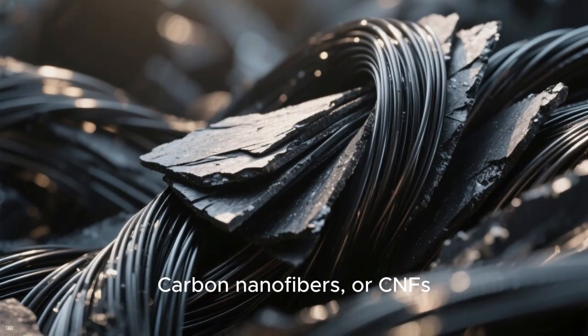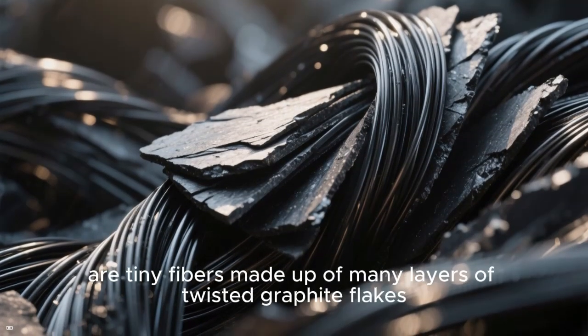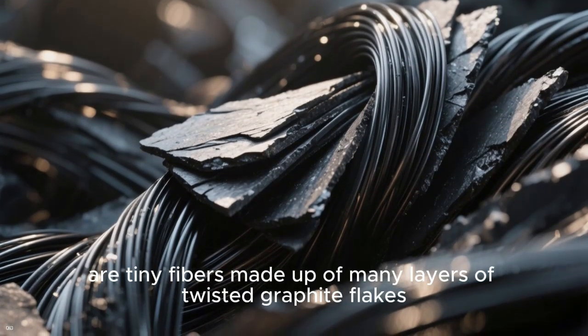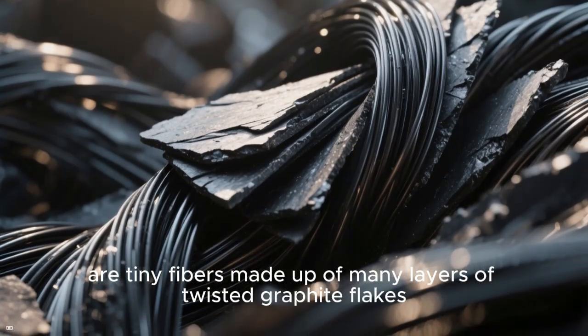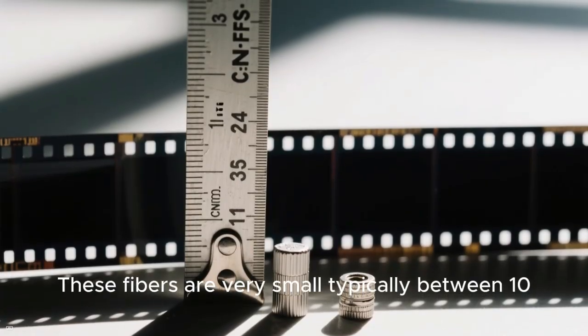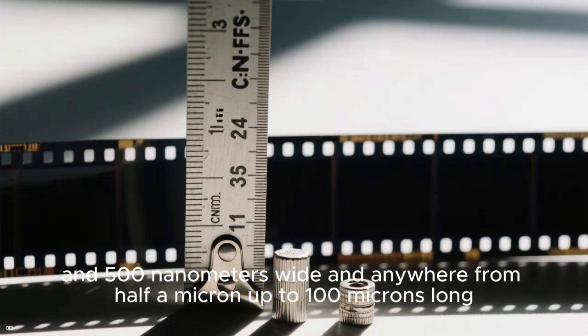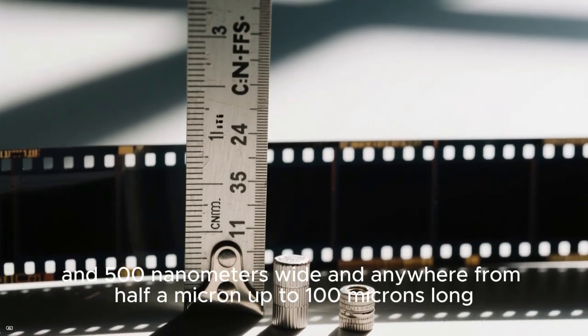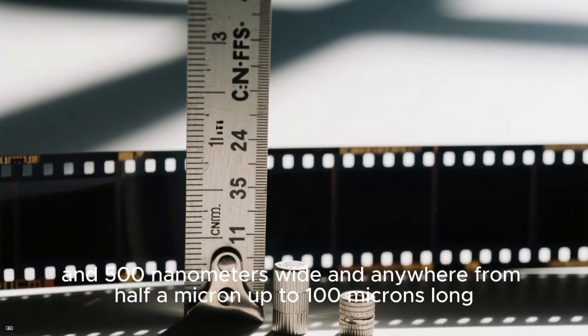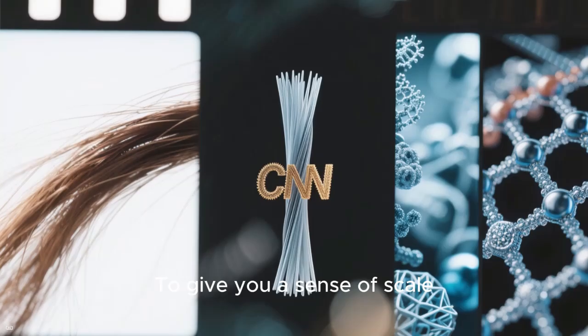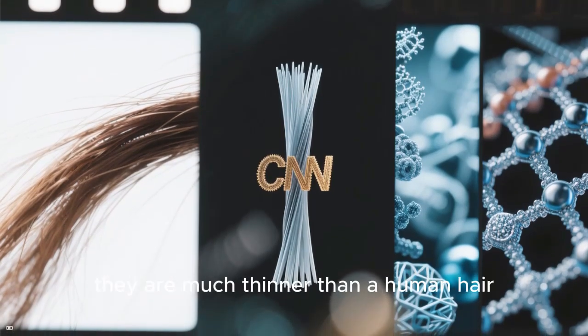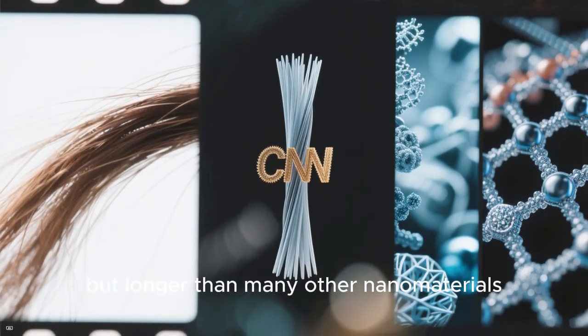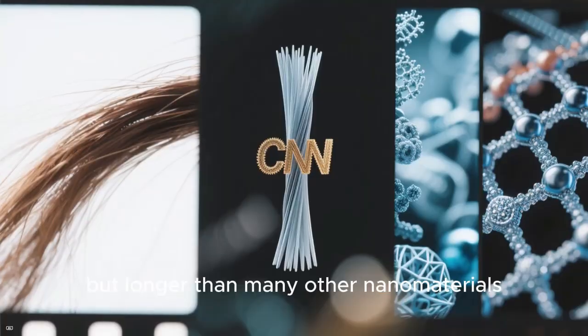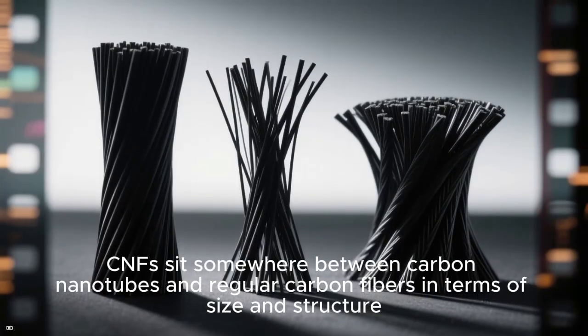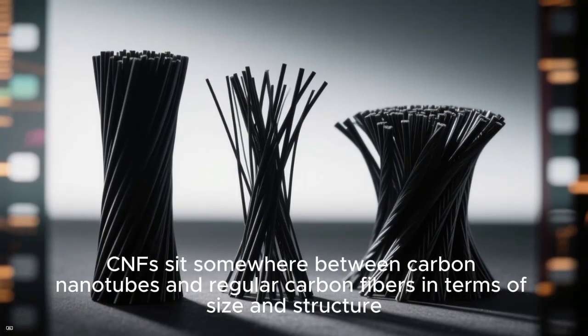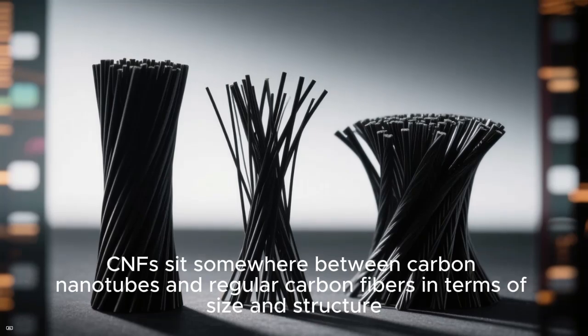Carbon nanofibers, or CNFs, are tiny fibers made up of many layers of twisted graphite flakes. These fibers are very small, typically between 10 and 500 nanometers wide and anywhere from half a micron up to 100 microns long. To give you a sense of scale, they are much thinner than a human hair, but longer than many other nanomaterials. CNFs sit somewhere between carbon nanotubes and regular carbon fibers in terms of size and structure.